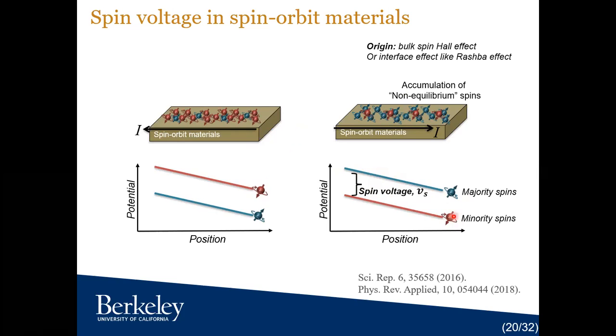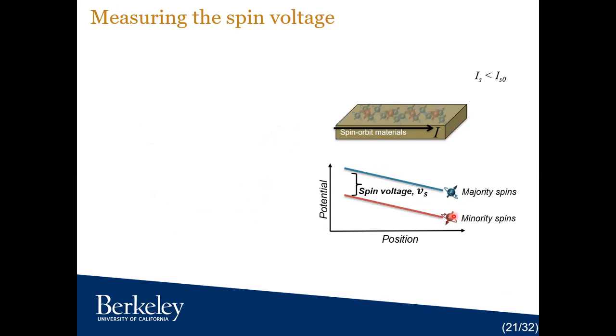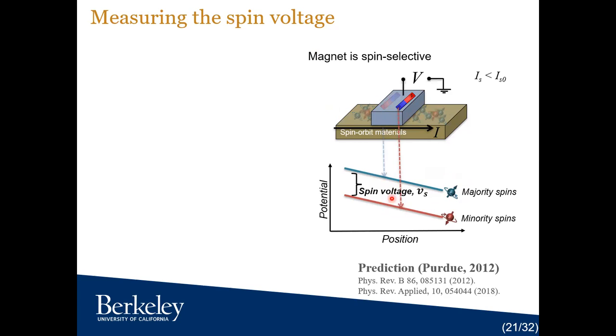But for that, we need a spin selective contact, and magnetic contacts are quite spin selective. If you have a magnet that's aligned with the majority spins, it will measure this blue curve. And if you reverse your magnetization, and now it's aligned with the minority spins, it will measure this red curve. So this was a prediction from our group at Purdue. And what we said is that we should be able to measure this in terms of a voltage. So for two different magnetic states, the voltage will be different.